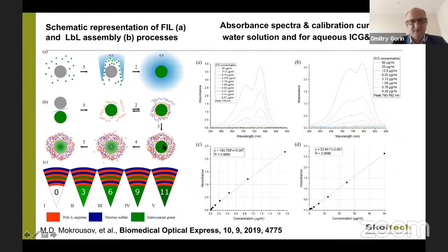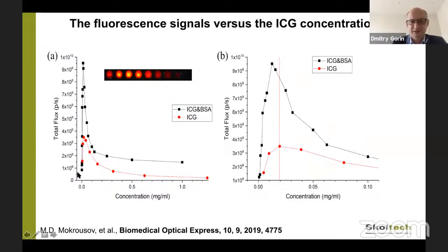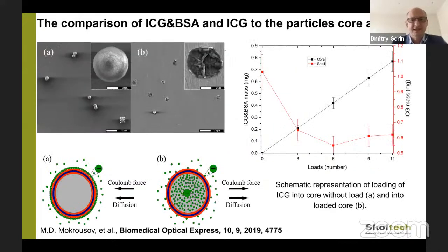How can we use this phenomenon? We use the self-quenching effect. Here you can see the dependence of fluorescence on the concentration. Starting from some concentration, we can see an increase of fluorescence and then a decrease of fluorescence. And of course, if fluorescence decreases, we can have more energy transfer to thermoelastic expansion, and this is very important for photoacoustics. And we also found that if we have preloading substances inside of the shell, we obtained less absorption of dye on the shell.